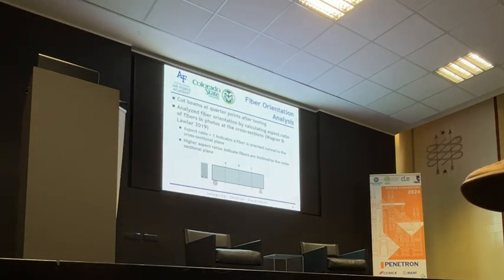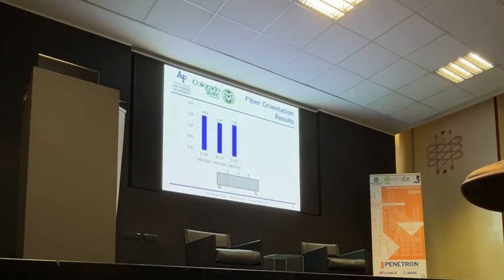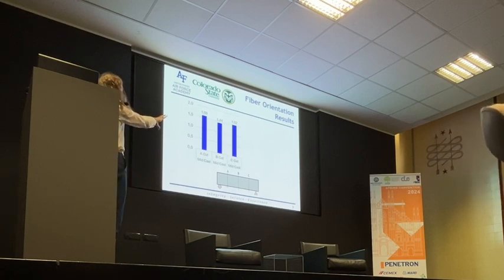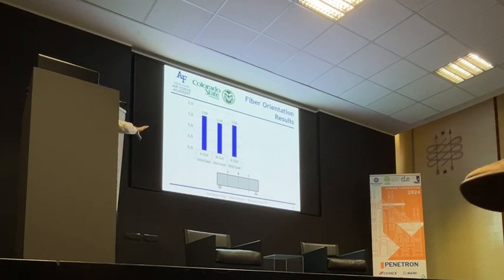So what happened with that? Well, we found that with pouring in the middle, so pouring at location B, we had the smallest value of that aspect ratio. What that means is that the major axis was 1.44 times as long as the minor axis. So at B, we had specimens with fibers that were more perpendicular to that transverse plane than at the ends.